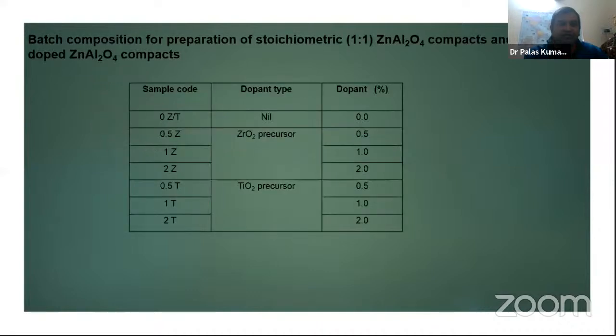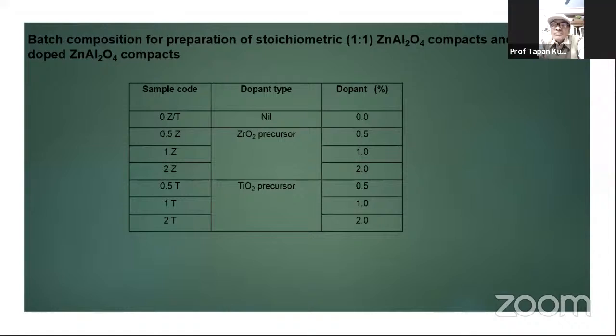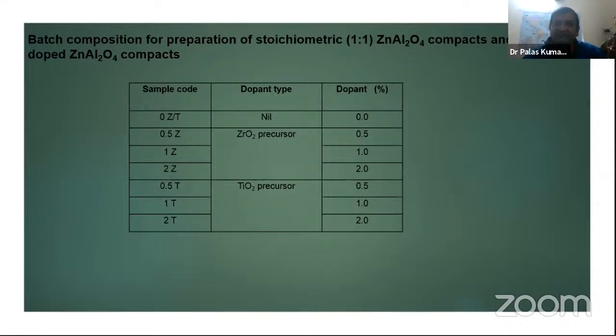So now coming to the batch composition, two separate groups were studied, one zirconia doped and one titanium doped, right? And for each group, there are 3 batches: 0.5, 1, and 2. This is basically weight by weight replacement, a dopant addition. So 0.5 dopant replacement of zirconia is coded as 0.5Z, 1 is 1Z, and 2 is 2Z. Similarly, titanium, T, right? So in total 7 batches, including the undoped version.